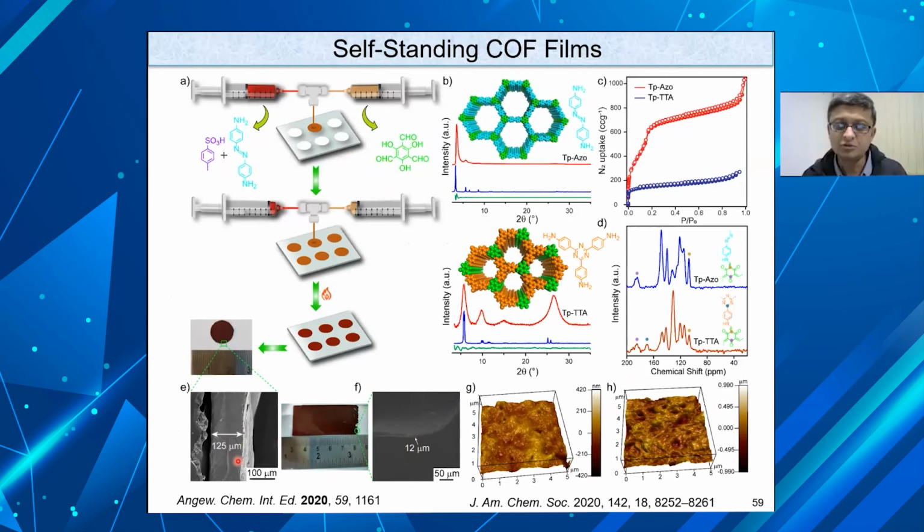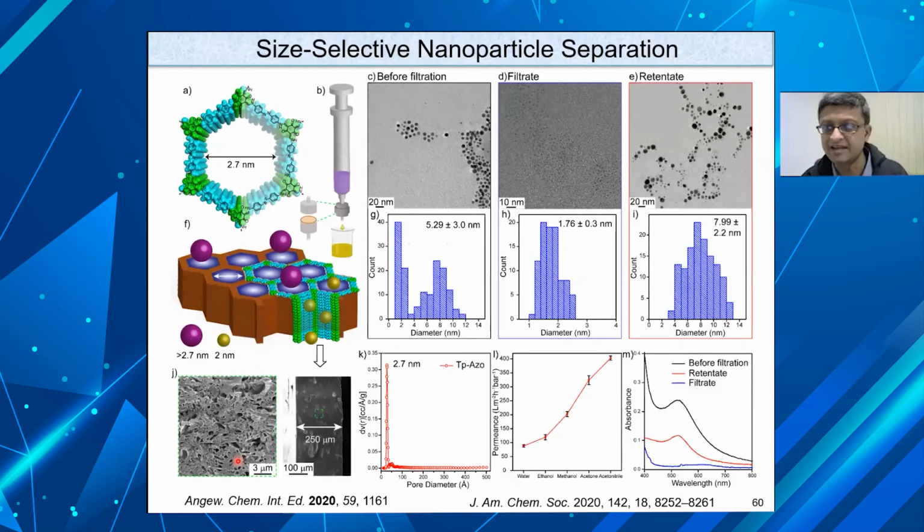So what we did, we just took the simple nanoparticles, which are commercially available. These are thiol-based nanoparticles, 2 nanometer, 4 nanometer, 10 nanometer. Run through it. So this is the cross section of the film that I want to show you, and you can see there are lots and lots of defects. So these nanoparticles will flow through it. These are very, very large defects, but at some point they will get stuck, and there is an alignment or orientation which lets these come through.